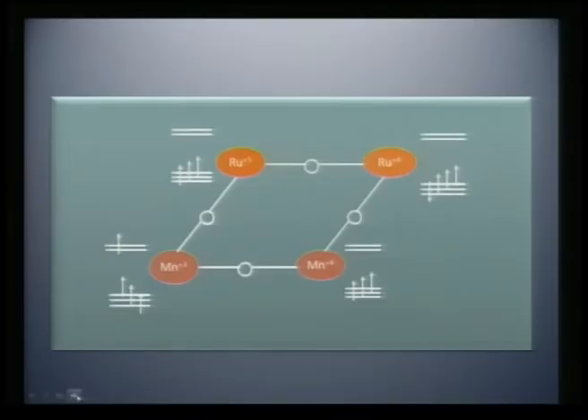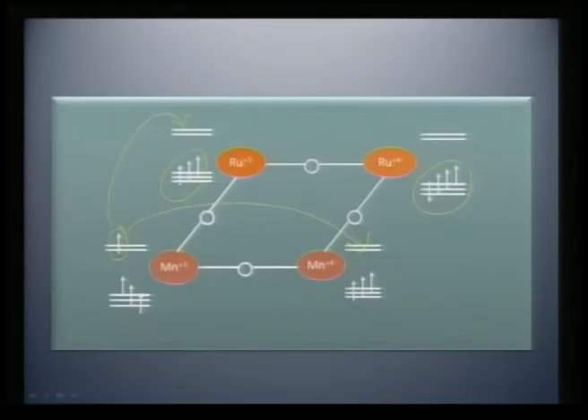So, we can sum up with a new double exchange model, where we say that the Mn3 plus Eg electron now has both ruthenium 4 plus and ruthenium 5 plus, and as a result this Eg electron can either go here or go to this empty orbital. Therefore, you have two double exchange pathways where you can drive this compound metallic and ferromagnetic, because you are providing a similar state. In other words, this Mn 4 plus is isoelectronic and has isoorbitals like ruthenium, which makes this a more important compound to study.